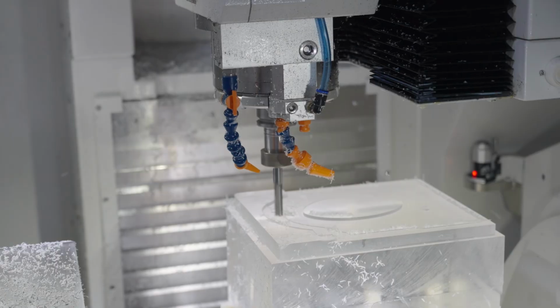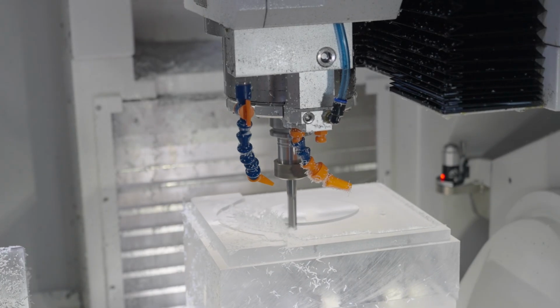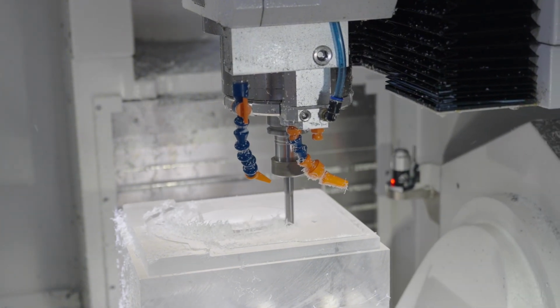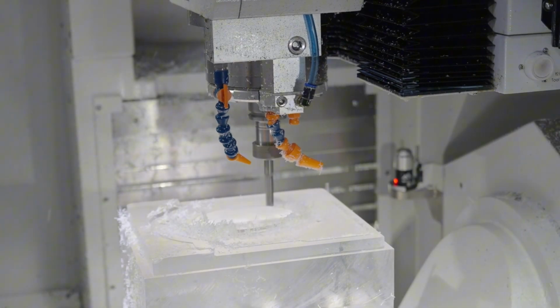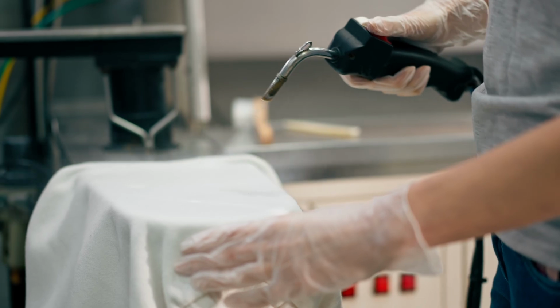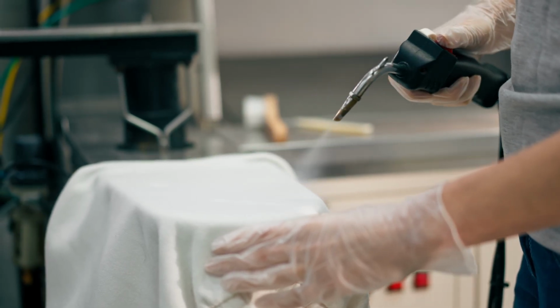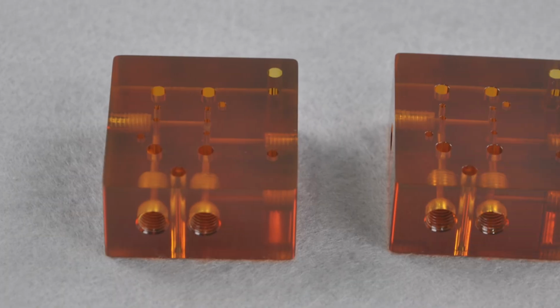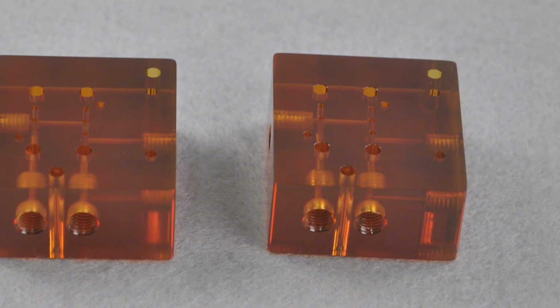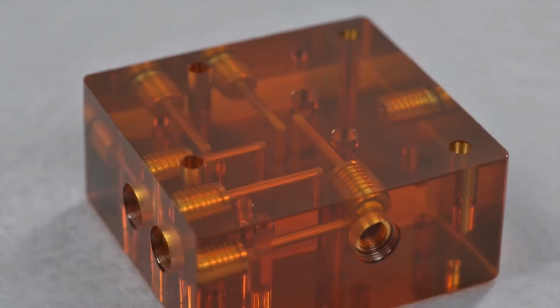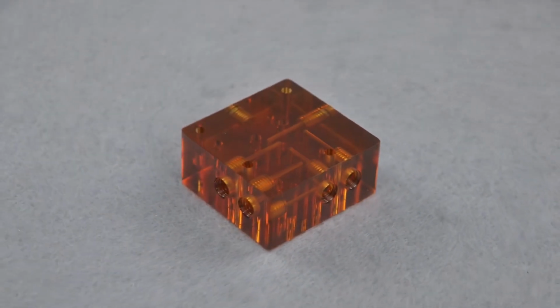Although the material itself is transparent, CNC machining leaves the surface frosted, reducing clarity and making the internal flow channels hard to see. WayKen's solution is that after CNC finishing, add a vapor polishing step. It restores optical clarity to the inner walls of the flow channels. Final results: transparency meets visual inspection requirements, and the mechanical performance meets specifications.